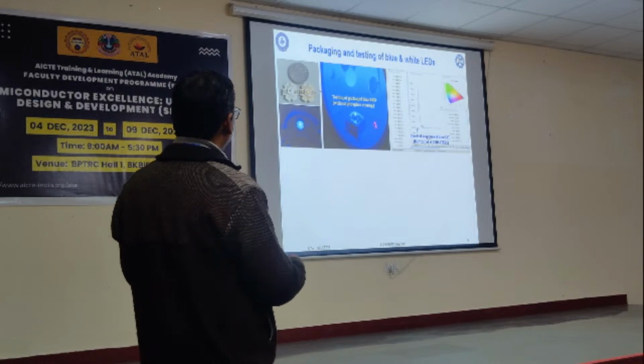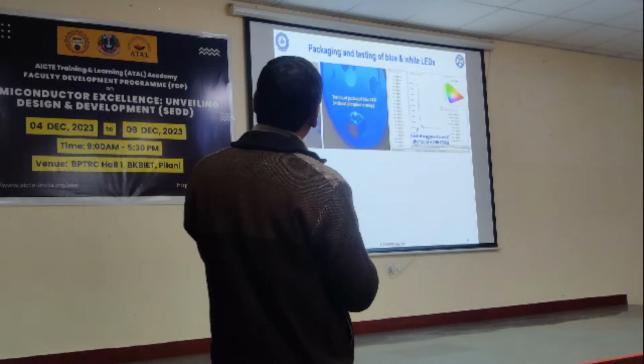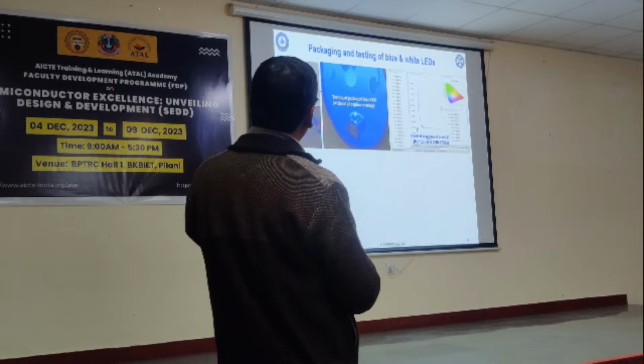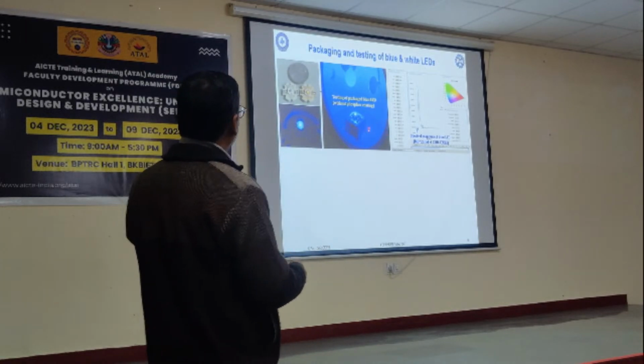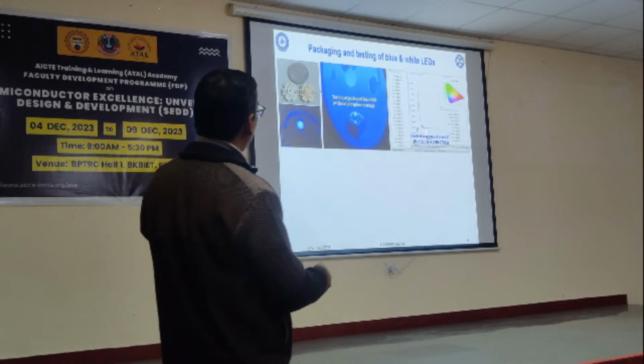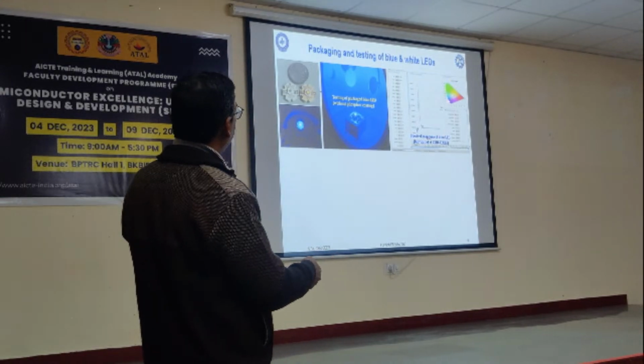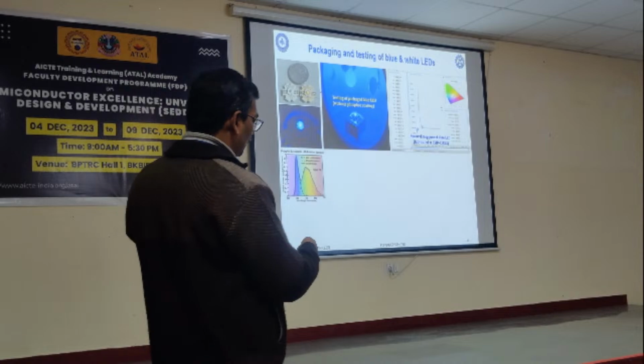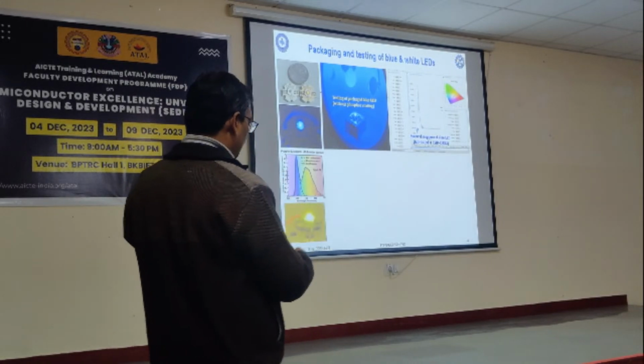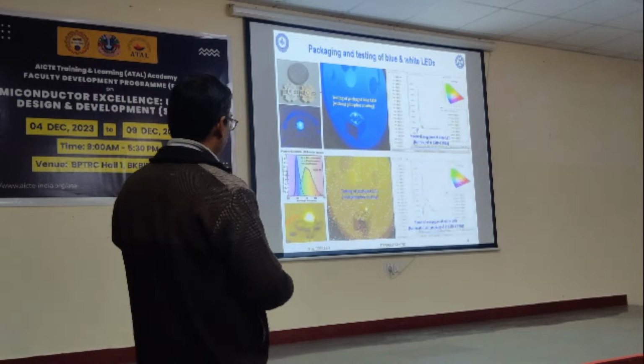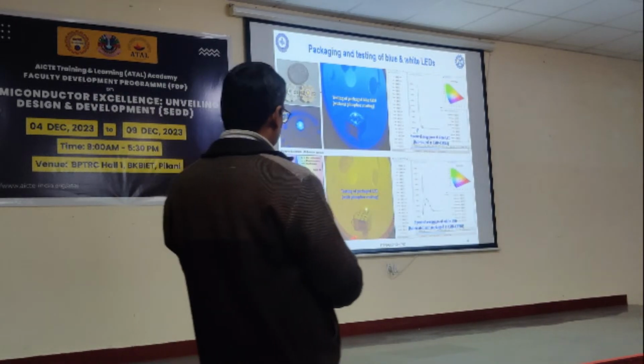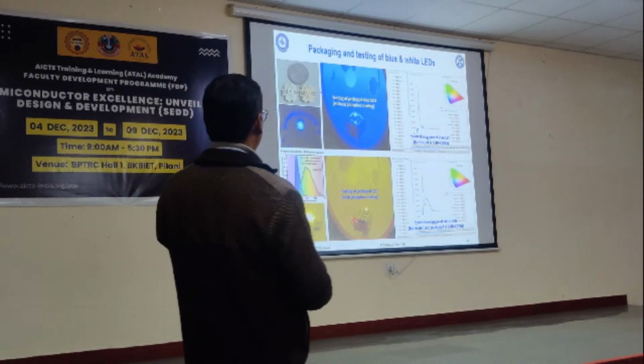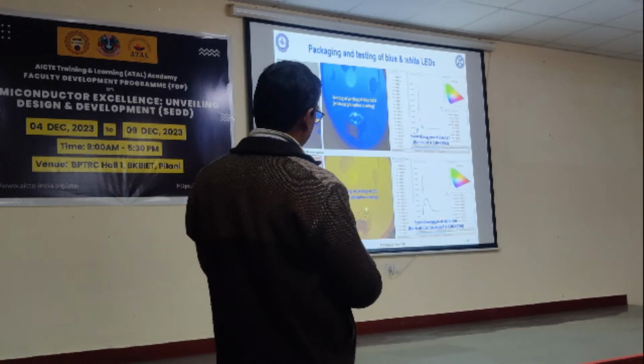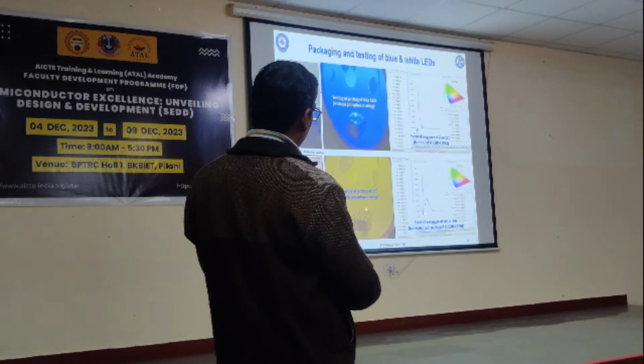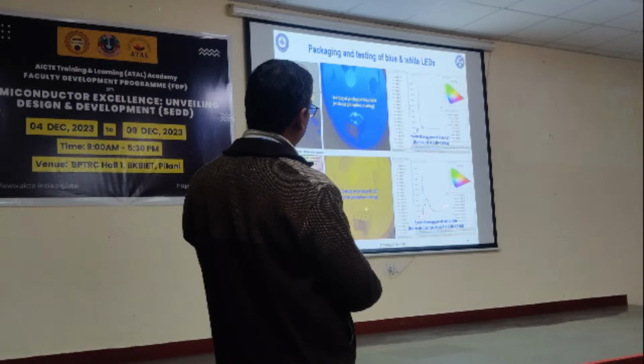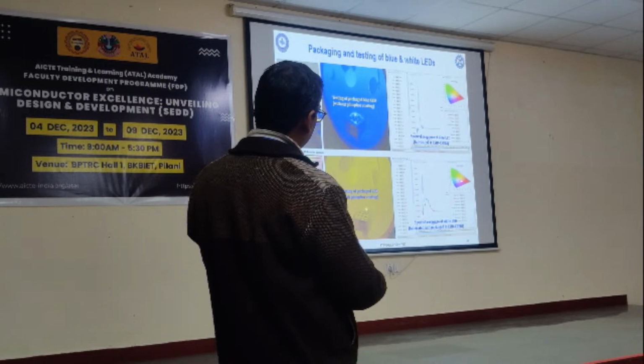So these are the fabricated chips. We tested the blue LED in the LED characterization system, the emission of the blue light and the position of the blue light here. After yellow phosphor coating, we get the yellow light. Again, we can test in the goniometric chamber, the LED characterization system. This is the blue combination with the yellow light combination, and this is the point where we are getting the white light.